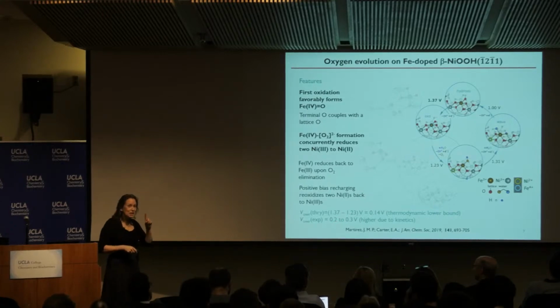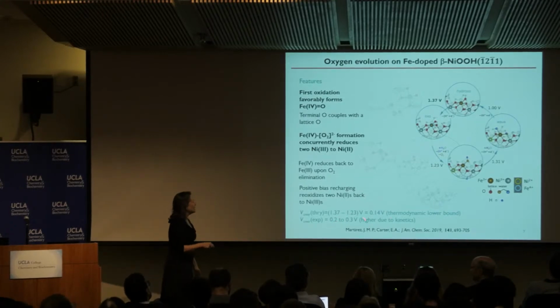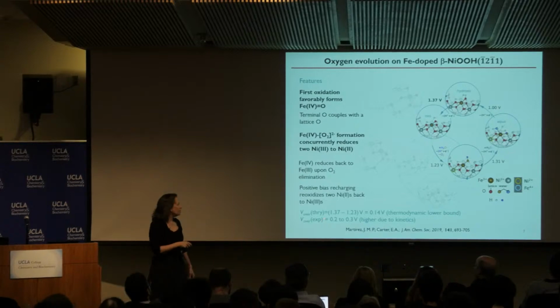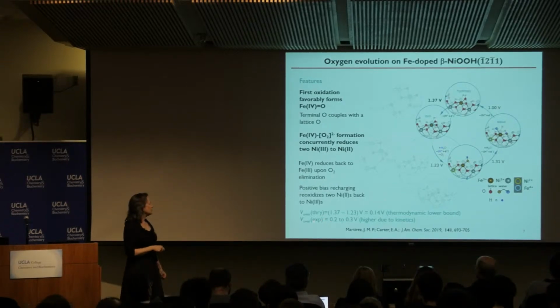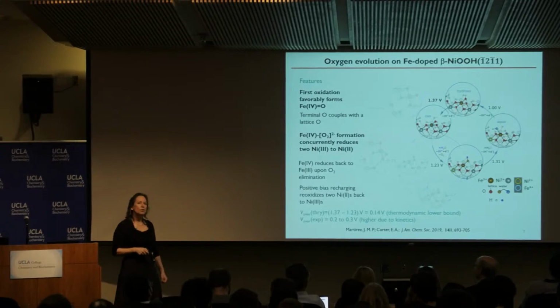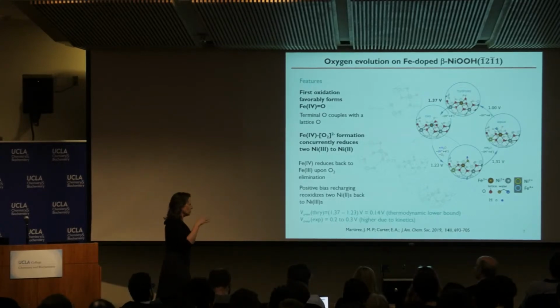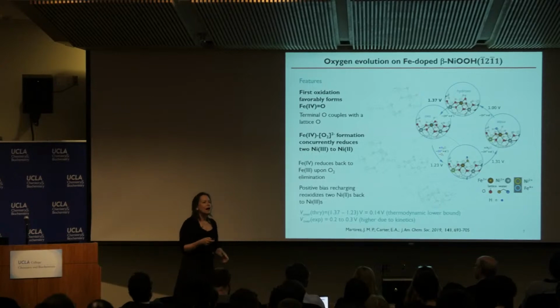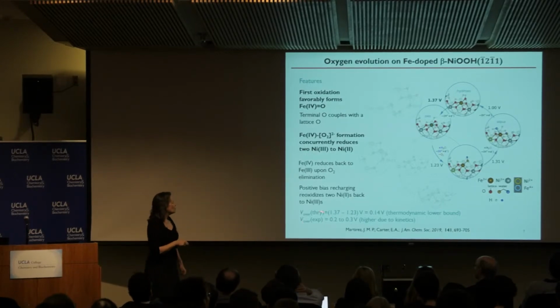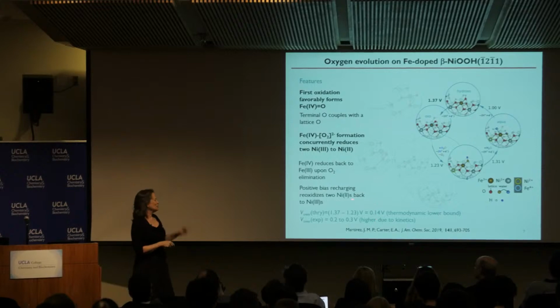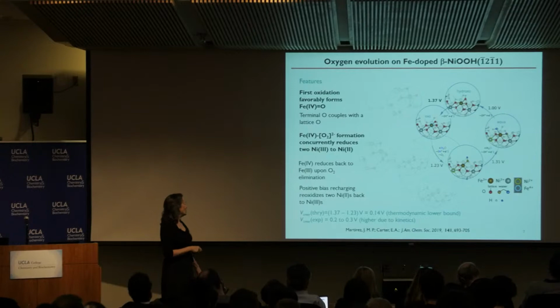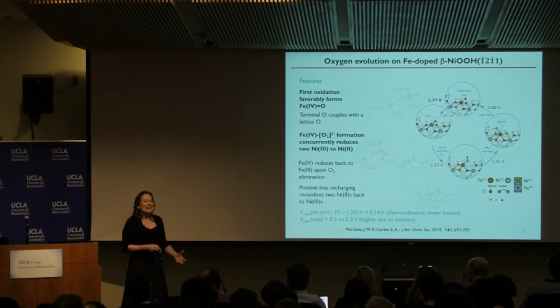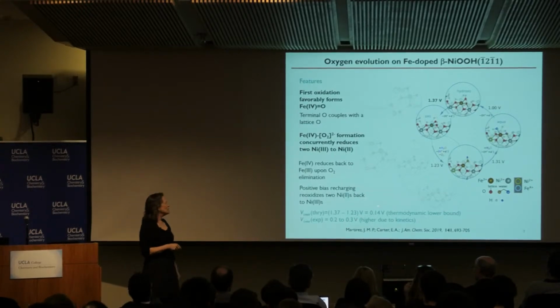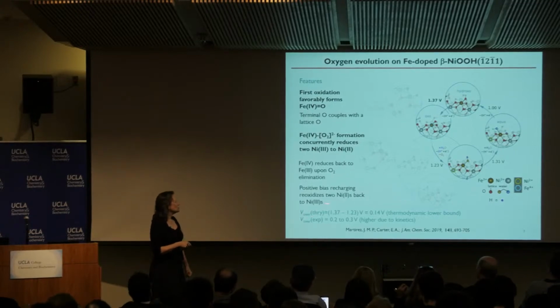So that's important because this is a lower bound, and it's higher because there is a bit of a barrier, no doubt, somewhere along the way, and that's why the experimental value is 0.2 to 0.3 volts. Contrast this with earlier theoretical work, which said, we were able to calculate an overpotential that matches experiment of something like 0.25 to 0.3, 0.35 volts or something like that. That's not physically correct, right?